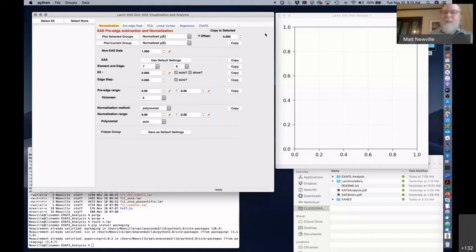So these pre-edge peaks, or these peaks on the edge, are often interpretable as the first unoccupied states, and it's easy to think of them as atomic levels. You could also say that's where the Fermi level is. In the XAS community, we're often a little cavalier about saying where the Fermi level is. It's the first unoccupied level, but it might belong to the atom or belong to the hybridized levels of the atom with its neighbors.